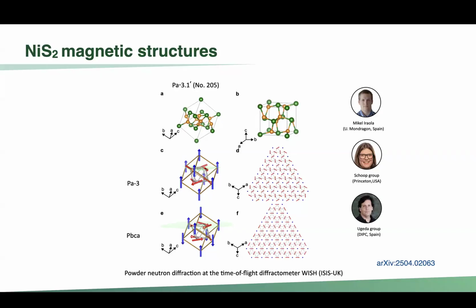So we have two magnetic phases. One is the cubic, with the very interesting case that all the magnetic moments follow the bonds. So we only break time reversal symmetry, and the spatial symmetry of the cubic structure remains. It's an antiferromagnet, maybe an altermagnet too. And the magnetic transition goes to an orthorhombic one, where we get some sort of a spin Kagome lattice that is ferromagnetic. Okay.